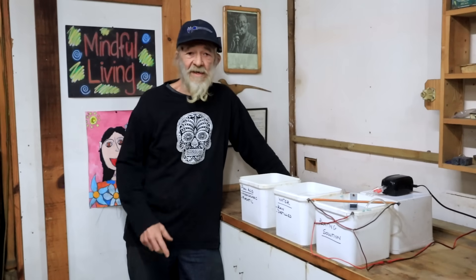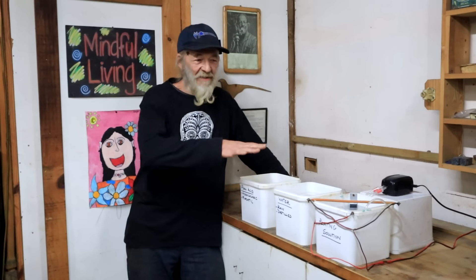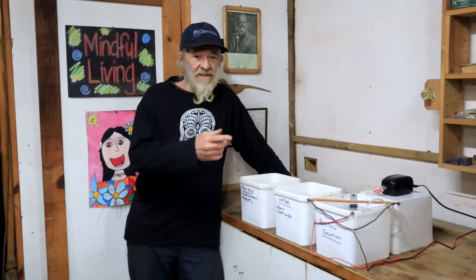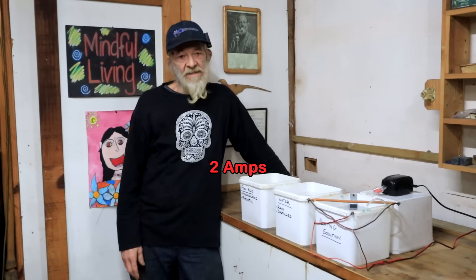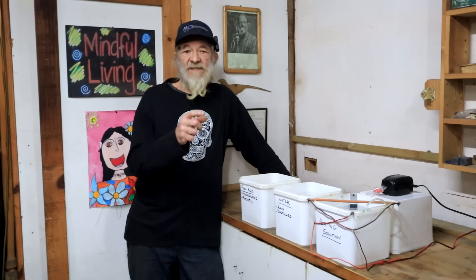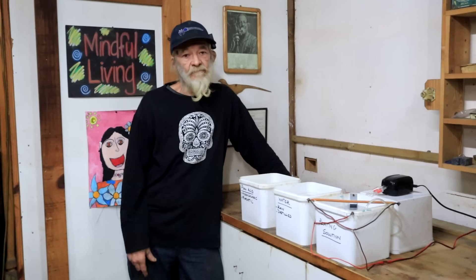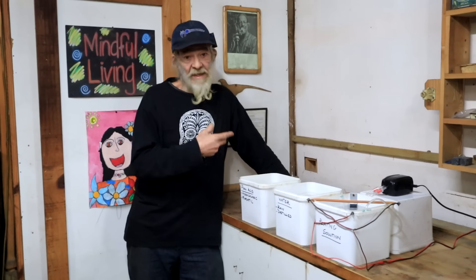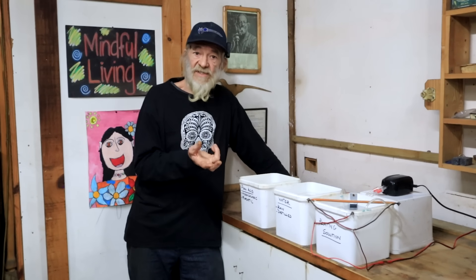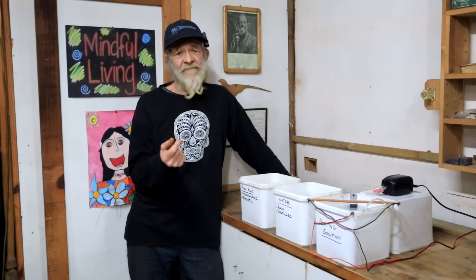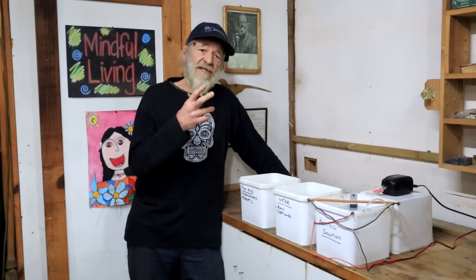I'm just playing it by ear or rather by eye. Occasionally, inspecting my parts during the plating process, there's no issue to take it out and have a quick look at it and sticking it back in. Keeping in mind that I have a fixed current supply of 2 amps. I have been experimenting with plating time and depending on the number and the size of the parts that I do in one go, it seems that around 20 minutes is the longest period I use. It is my understanding that lower current per square inch will result in finer crystals but obviously plating time will be longer. And higher current will obviously plate faster but it can apparently cause rough deposits and even burning. If you don't have an adjustable power supply like me, a little experimenting is the order of the day. It doesn't work too well, you can just clean out the part and try it in a different manner.